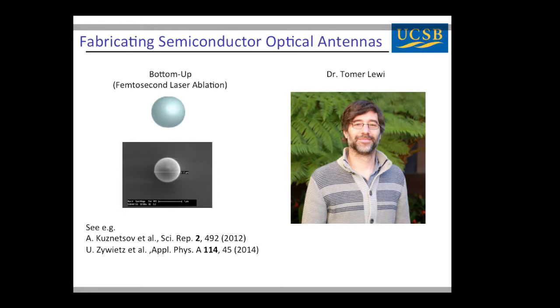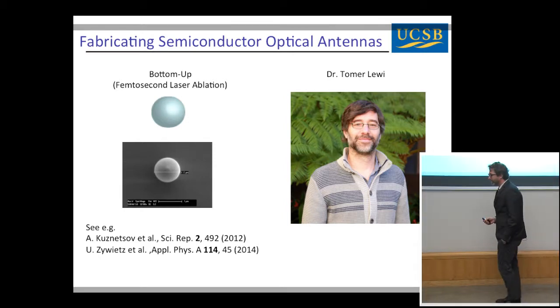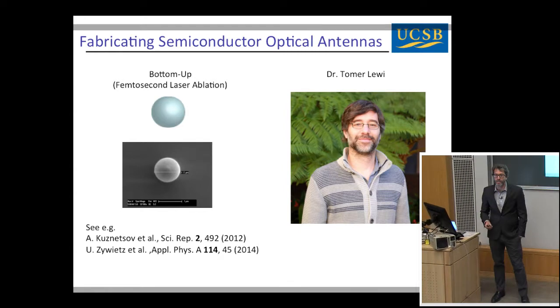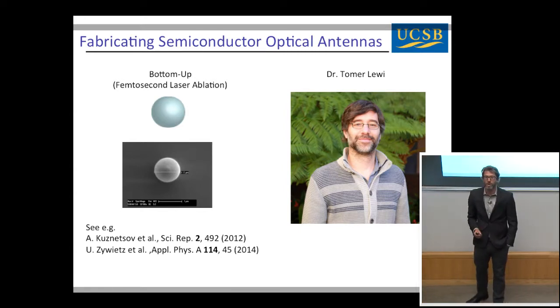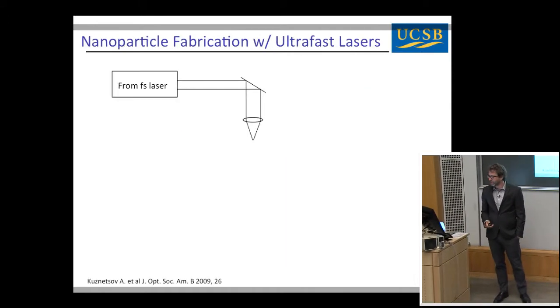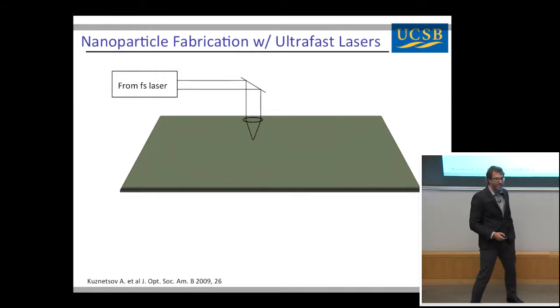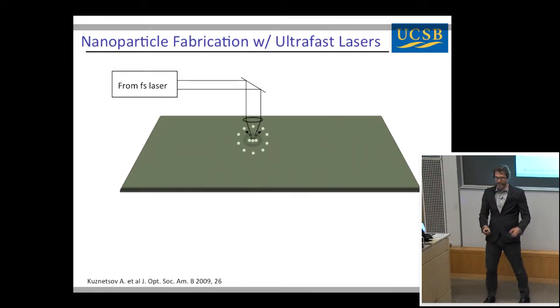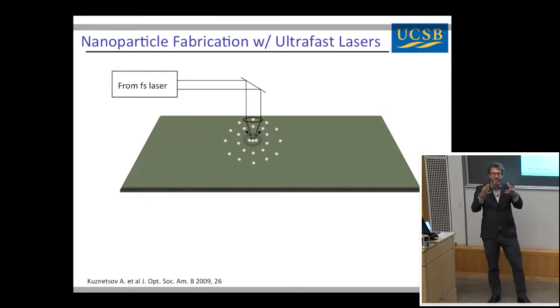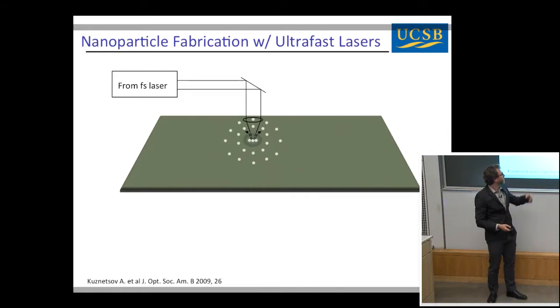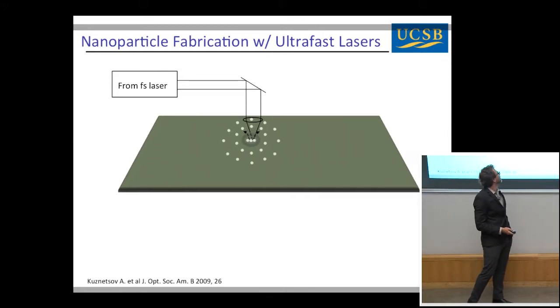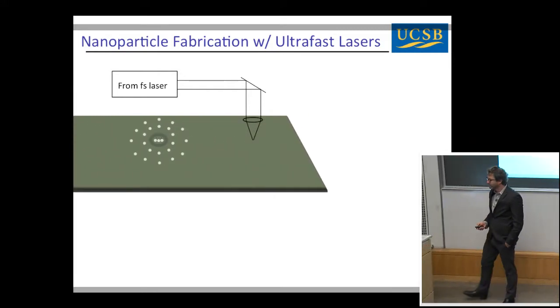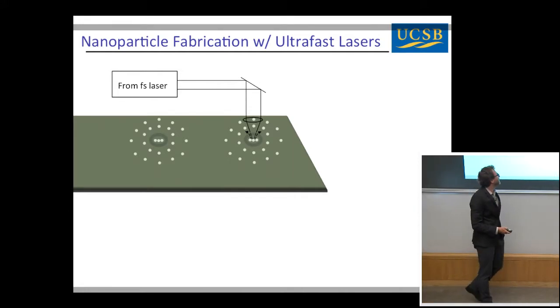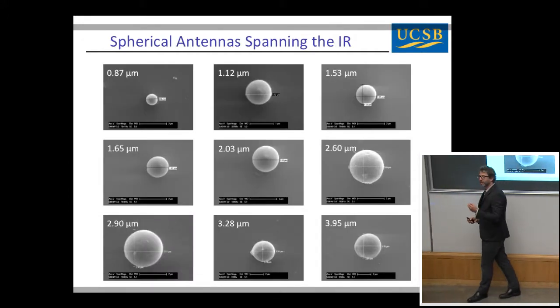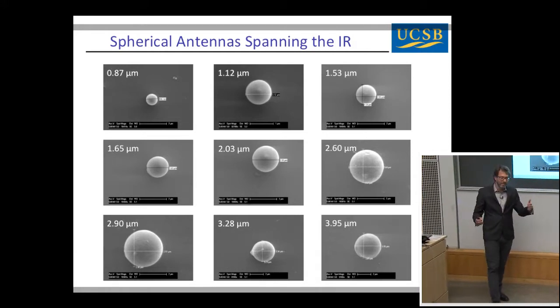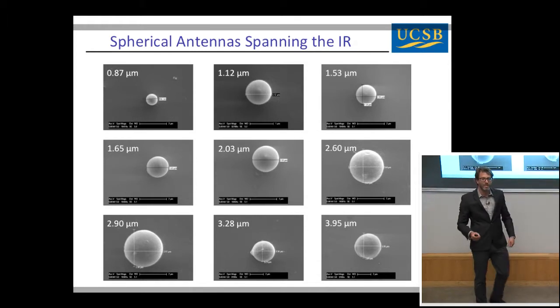In the meantime, my postdoc, Tomer Lewi, was looking at demonstrating these kinds of effects in actual silicon and germanium spheres that he fabricates with a bottom-up femtosecond laser machining approach. Okay? So the idea is we take a highly focused femtosecond laser, shine it on the surface of a semiconductor, and it hits the semiconductor, material ablates and cools as it comes off, and comes back to the surface. And so we decorate the surface with spheres, and we can move around and change the conditions, change the intensity or power of the laser. In doing so, we can create very nicely spherical semiconductor particles with sizes in this micron regime and with optical resonances that really span the infrared.